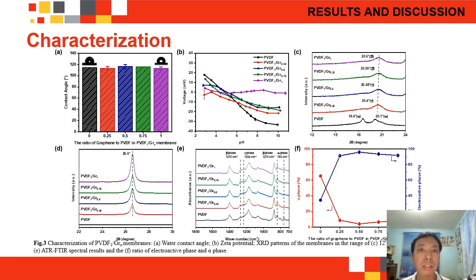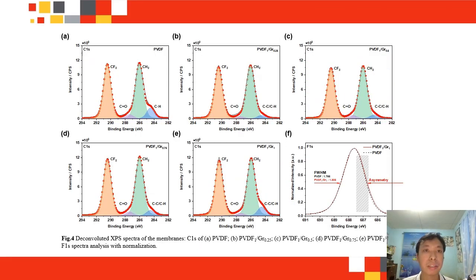This structural transition confirms the alignment of PVDF chains by graphene, enhancing the piezoelectricity of the membrane. XPS. XPS analysis was employed to investigate the chemical composition of PVDF1 graphene X membranes, with characteristic peaks corresponding to C1s, F1s, and O1s identified in the figure. The convolution of the C1s peak, as shown, reveals key features of the material.